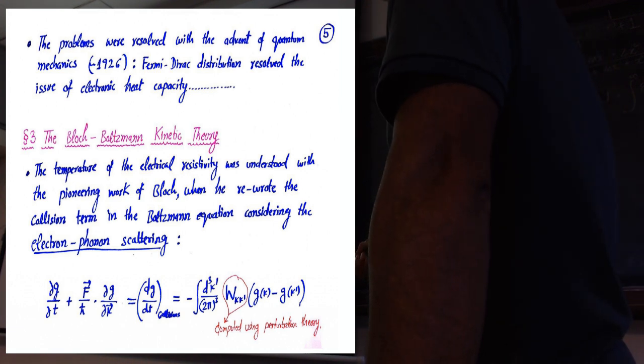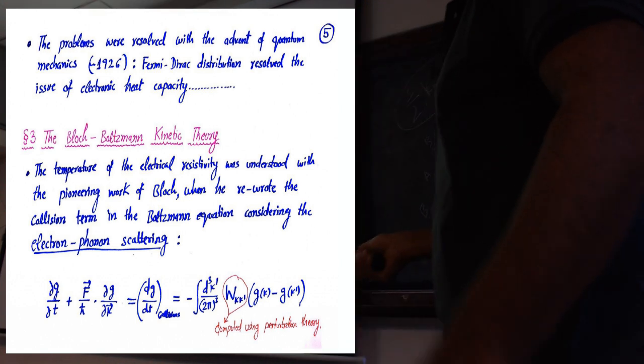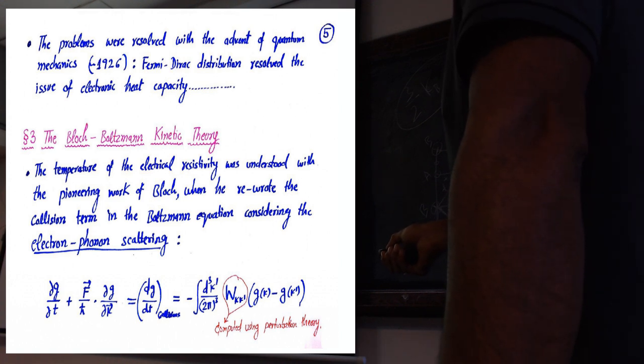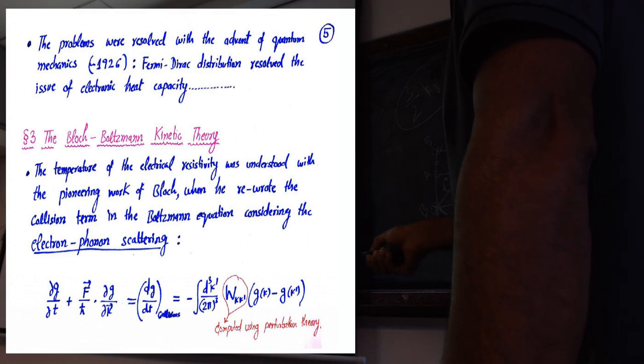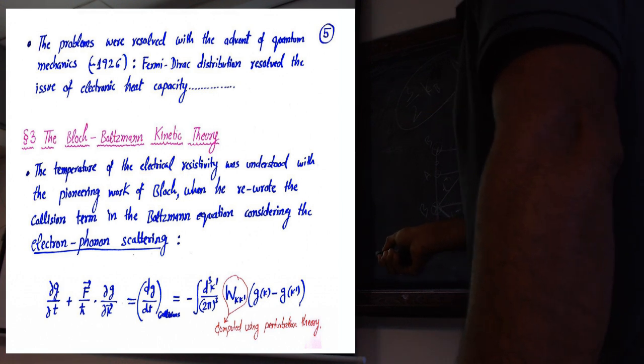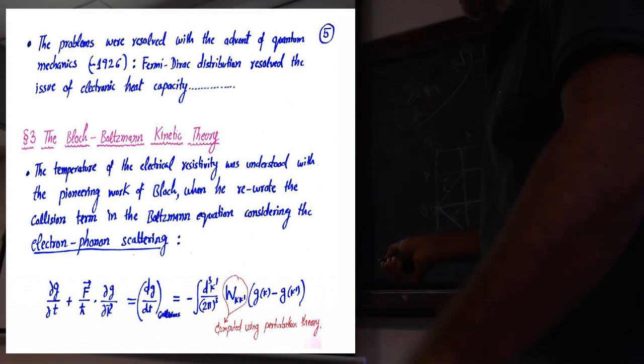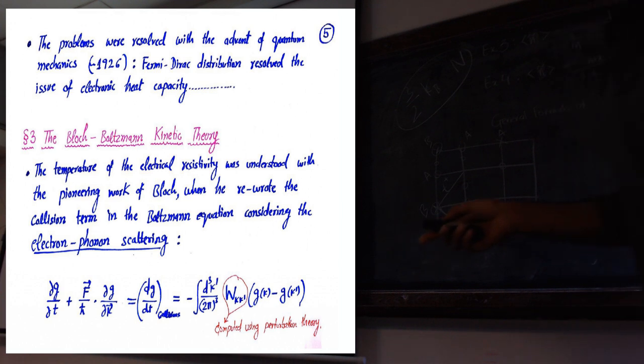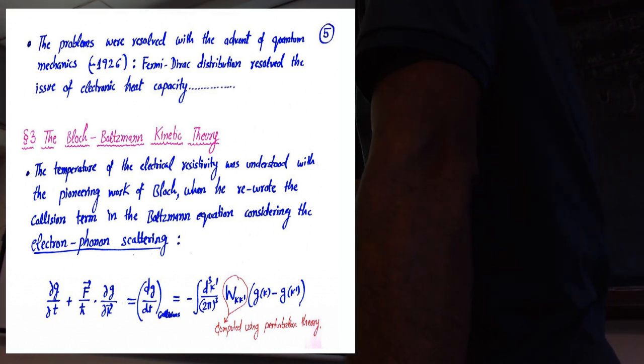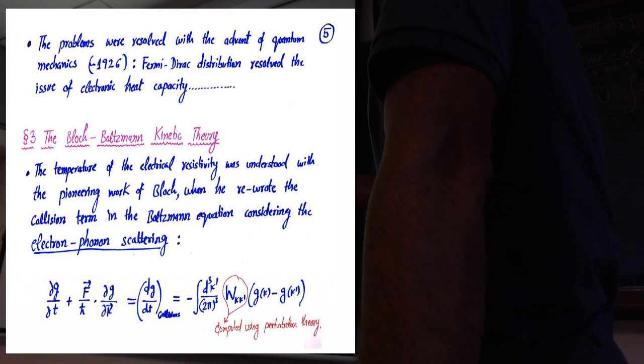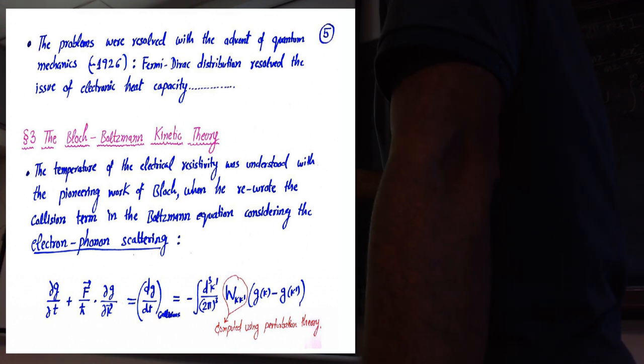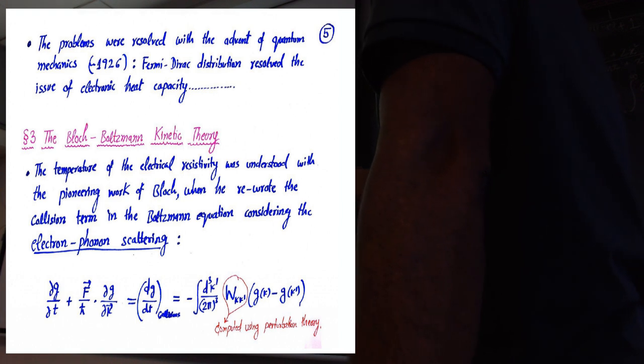It gives the rate at which an electron in the k prime state goes to the k state, or vice versa, by generating a phonon, for example. And this g_k has a minus sign because this is a loss, and the integral over k prime is how many electrons scattered from k prime go to k. This is the gain term, a positive term. So just gain minus loss, basically. And he solved this equation using this diagrammatic representation. K goes to k prime and generates a phonon, or k goes to k prime and absorbs a phonon with wave vector minus q. The momentum must be conserved.